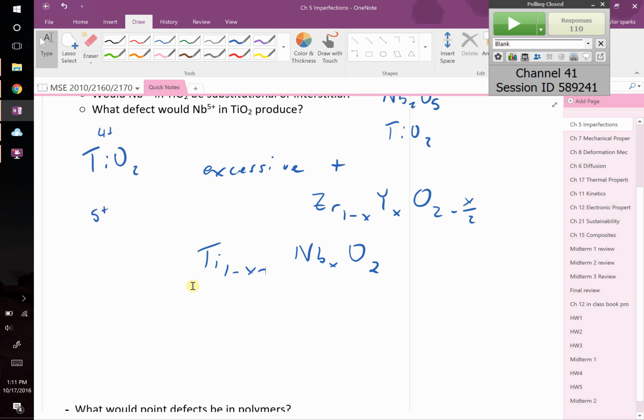Well, I had a different question. Okay. So when you take that extra titanium out, you're leaving a hole there. So that's a vacancy. It's now a titanium or a cation vacancy. So overall, the energy is more, I guess, desirable by having that hole than it is by having the extra. Yeah, we haven't talked about energy. This has to be energetically favorable for it to happen, right? You're giving it some entropy by adding 2 different types of cations. It likes that. That's disorder. But yeah, you're having bonds broken, so you're competing with that. In some systems, it will be favorable, in some it won't.